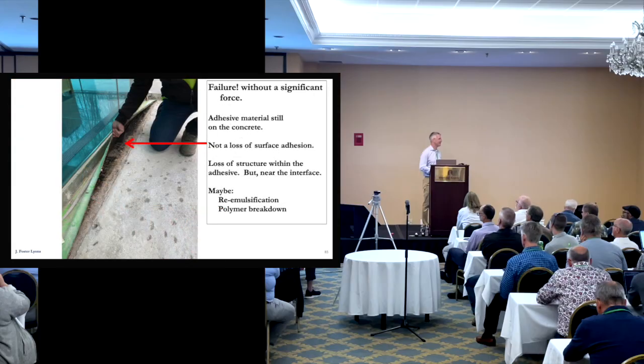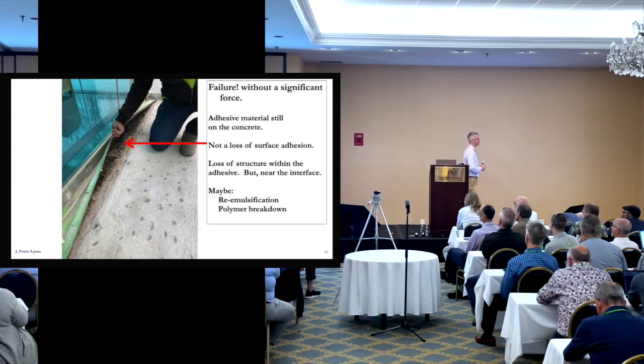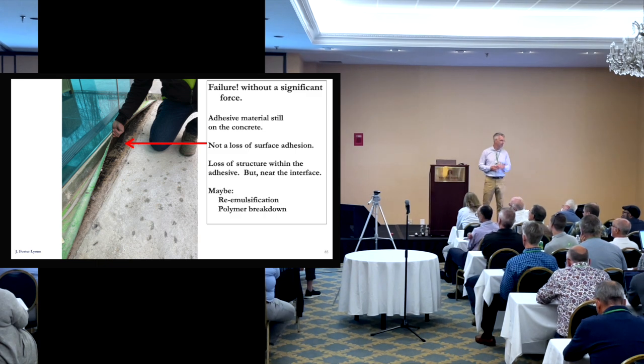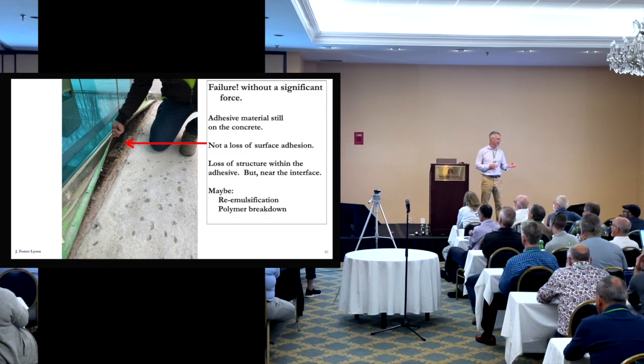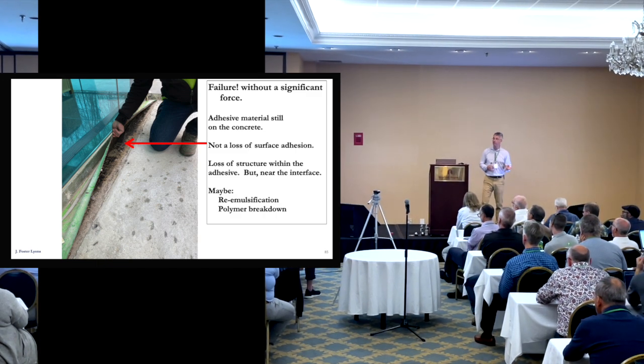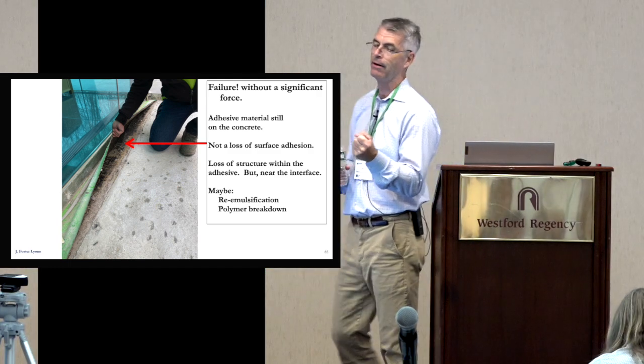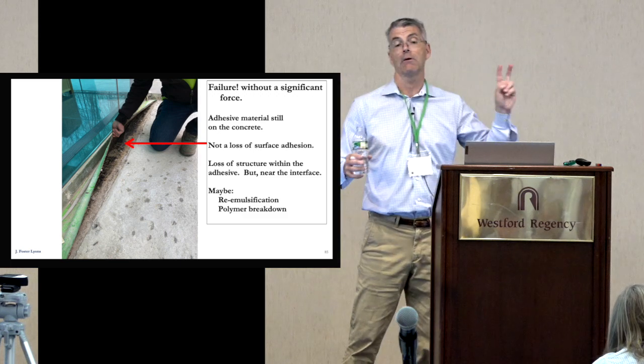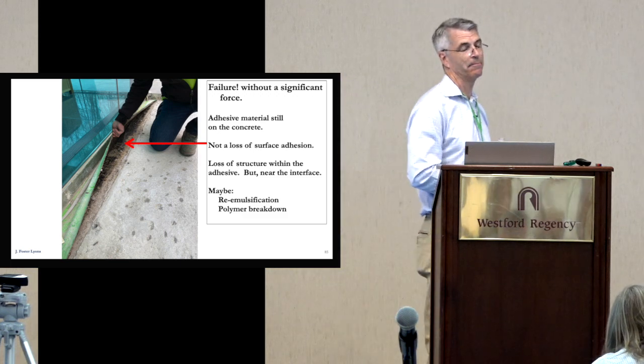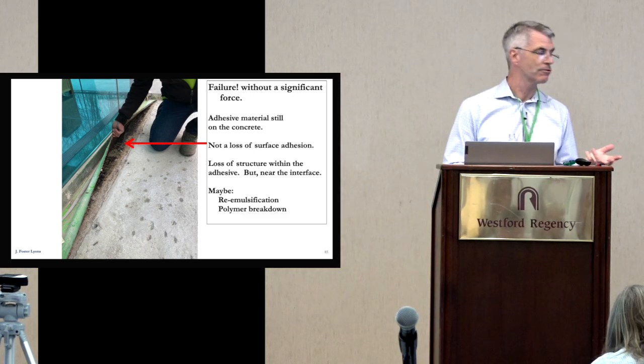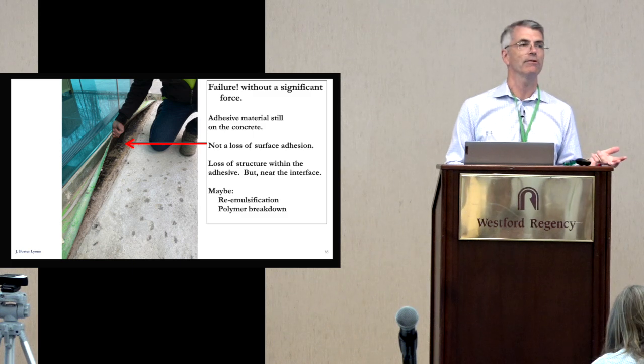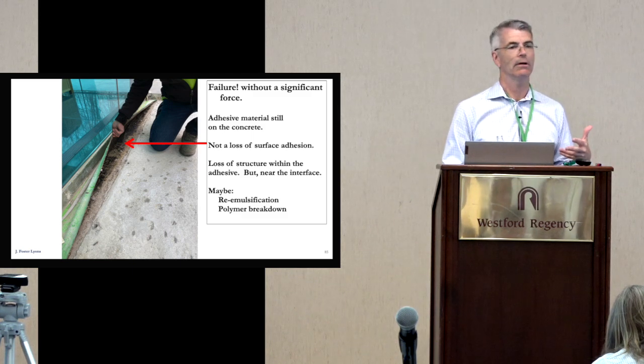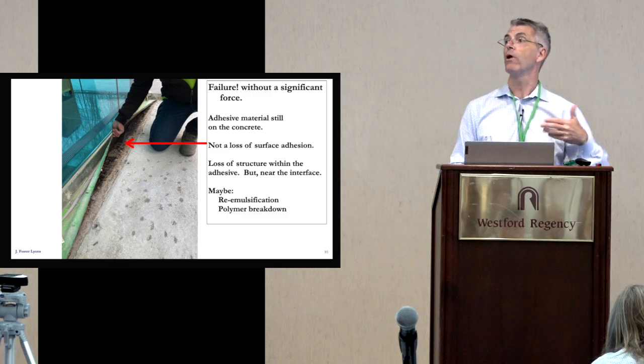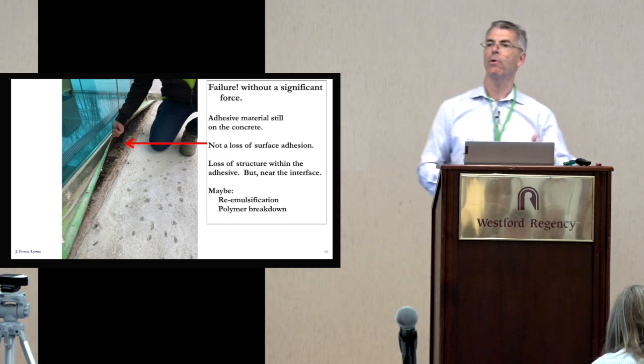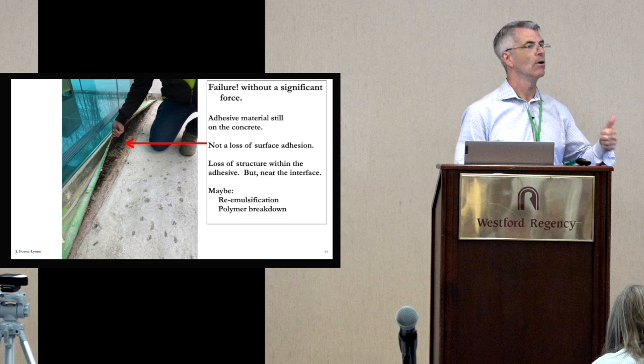This one is total failure. So that's the self-adhered material and the green stuff there on top, and that's concrete below it. And you can see that some of the adhesive material is still stuck to the concrete, right? And it's come apart cohesively, more or less. So these surface energy bonds still exist. So the material broke not right at the surface. It broke within the adhesive. So something went wrong with either the intermingling or the entanglement.